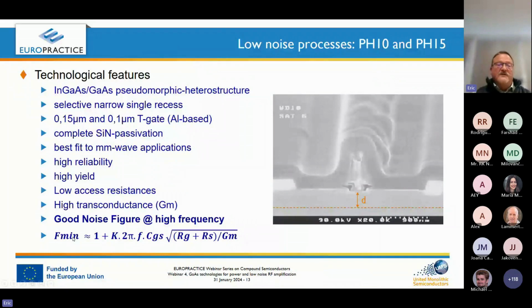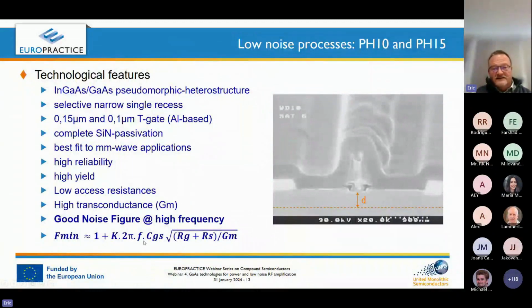You can see here the evolution of the minimum noise figure of the transistor, which is proportional to the frequency F, CGS, which is the capacitance from gate to source, multiplied by the square root of RG, the gate resistance, plus RS, divided by the transconductance. So if I can increase the transconductance and decrease the gate resistance and source resistance, then I can keep a noise figure as close as possible to 1. Of course, when you increase the frequency of the transistor, you will see the noise figure increasing. Unfortunately, but that's physics. So this is how we optimize the process for low noise.